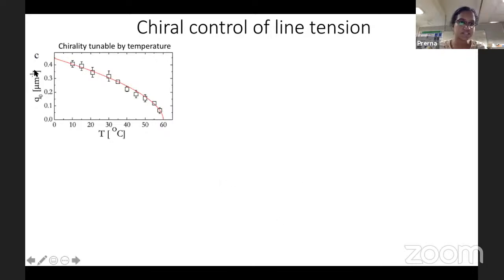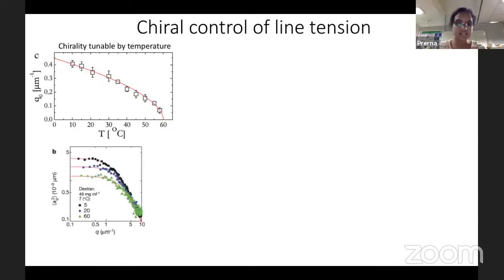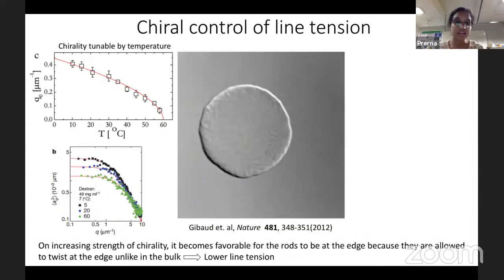And so here is the pitch of the cholesteric as a function of temperature. Essentially, by increasing the temperature, you can make the rods achiral. So what that does is that at very high strengths of chirality, that is at low temperature, when chirality dominates, the edge is going to become unstable. Why so? Essentially, when you increase the strength of the chirality, it is favorable for the rods to be at the edge, because that's where they can satisfy their chiral interactions.